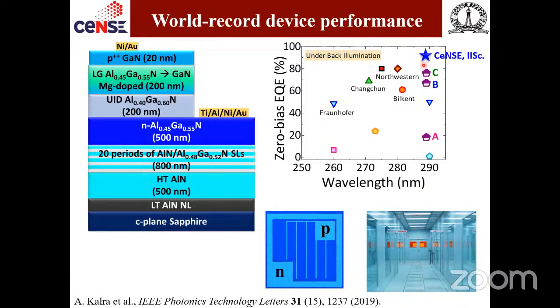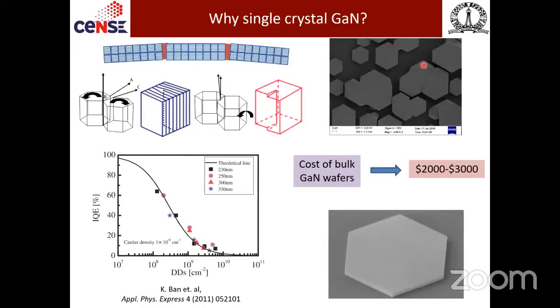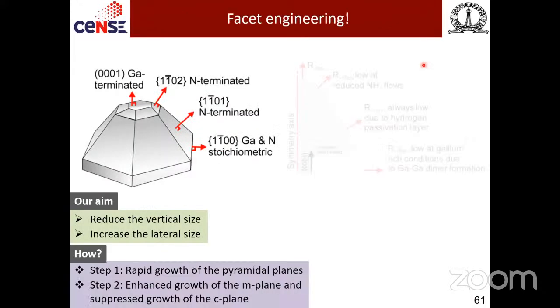And all of this was only possible by a careful optimization of materials at atomic scales, all those defects that I talked about. Only when you take care of these defects and try to understand how these defects impact your device performance, can you make very clean material, and that's how you can enable such high efficiency. So this was one of the biggest successes that we could work on during our PhD. Again, we made amazing results, but in the interest of time, I'll have to skip through all these results.